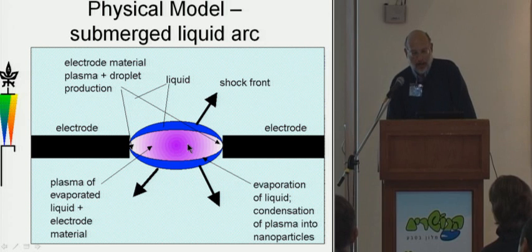Okay. Now, either during the process or after the end of the pulse, the condensable part of this material condenses. And it happens at a very fast time scale. During the process, there's an extremely high gradient between temperatures that possibly are around 10,000 degrees, for sure around 4,000 degrees in the plasma, to basically room temperature in the liquid. And the gradient is very, very large. So I think we have some condensation occurring at this interface, but there's not a lot of time for it to happen. And therefore, the size of the condensates is very small.